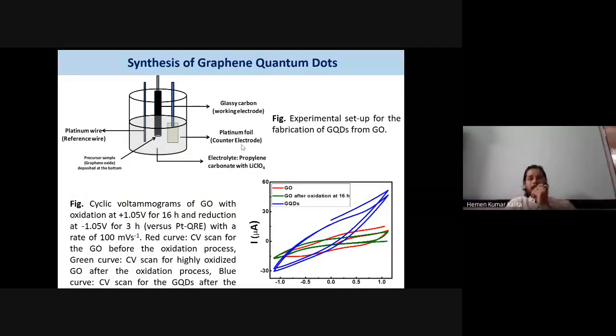So I'll just give you the basics. In the synthesis process, we have taken an electrochemical setup where there are three electrodes. One is the working electrode, another is the counter electrode, and the third one is the reference electrode. The working electrode is a glassy carbon electrode, the counter electrode is a platinum foil, and the reference electrode is a platinum wire. These are very standard electrodes which people use for electrochemical reactions. The electrolyte here is propylene carbonate and lithium perchlorate, and the precursor which we have used for synthesizing graphene quantum dot is graphene oxide.